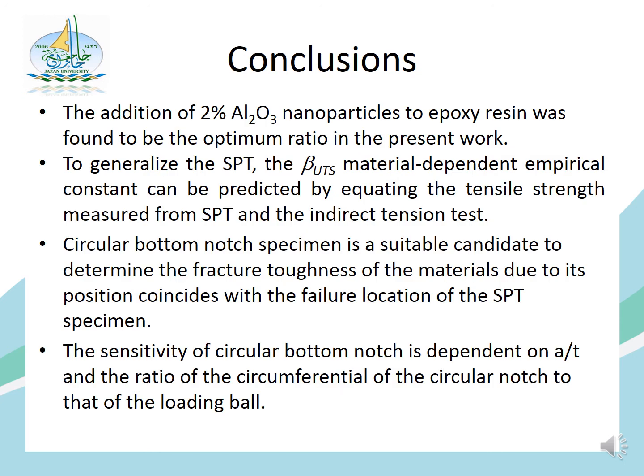Here we try to get some of the conclusions. For the main objective, the addition of 2 percent aluminum oxide nanoparticles to epoxy resin was found to be the optimum ratio in the present work. Also, to generalize the small punch test, the material-dependent empirical constant beta UTS can be predicted by equating the tensile strength measured from the small punch test and the indirect tension test.